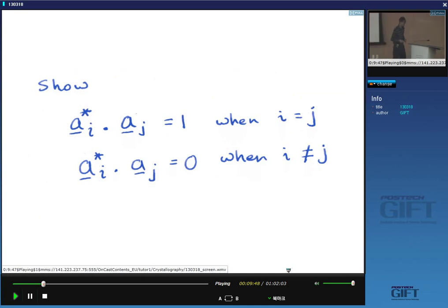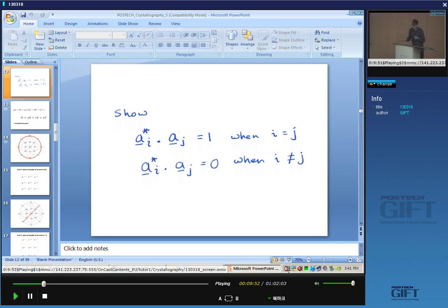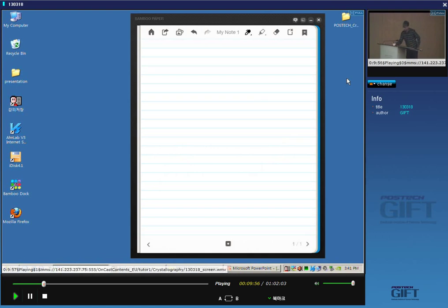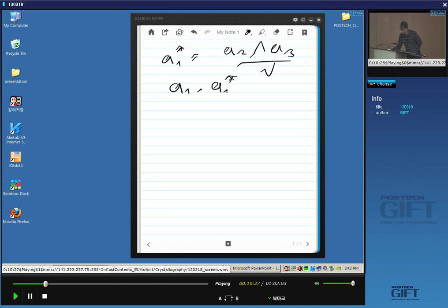Now, let me just, so we've got that A1 star is equal to A2 cross A3 over the volume, right? So what happens if I take A1 dot A1 star? A1 star is A2 cross A3 divided by the volume of the cell. What happens if I take a dot product with this? Yeah, it's 1, isn't it? Because A1 dot A2 cross A3 is simply the volume of the cell. Okay, so this will be equal to 1.